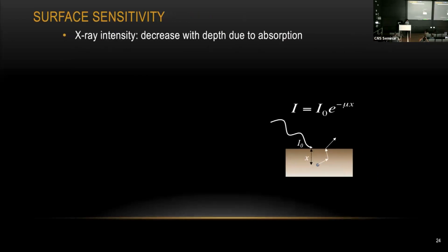And the second dependence is the surface sensitivity, and that pretty much has two parts. The first part depends on your X-ray beam. We know the X-ray beam can actually penetrate quite deep. But since we are getting the photoelectron out from the surface, you can mostly only pick out the photoelectrons right from the top region of your material. The X-ray beam will attenuate quite a lot when going into your sample. So only a top portion of your sample can have signal moving out from the surface, and anything underneath, we're not going to pick out any signal.